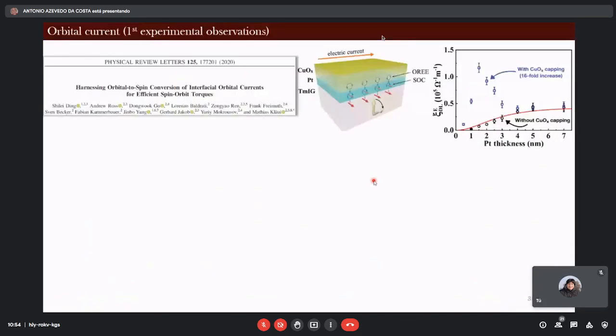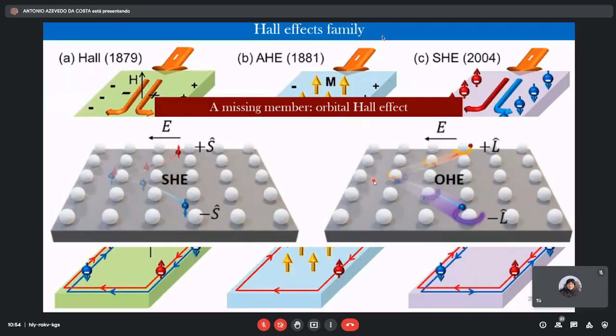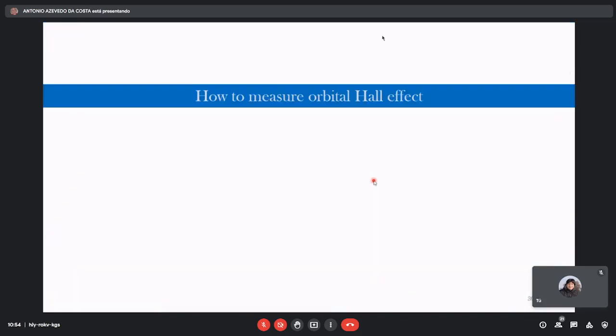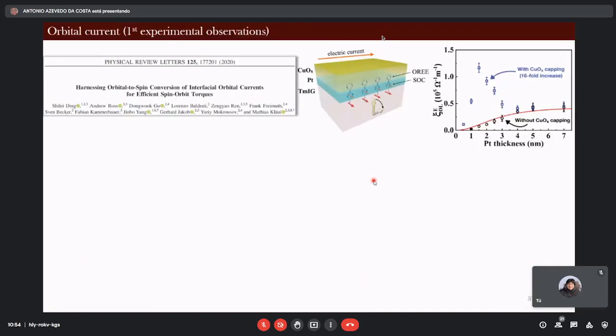The orbital Hall effect can be measured using different schemes. The first experimental work is this one, from 2 years ago, in which they use transport measurement in a material made of a ferromagnetic insulator, similar to thulium iron garnet, platinum, and copper oxide. In this case, they measured the torque transferred from the electric current which flows in the platinum to the magnetization of this ferromagnetic material. I'm just finishing, a few more slides.